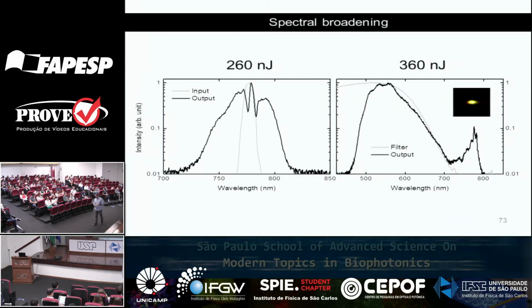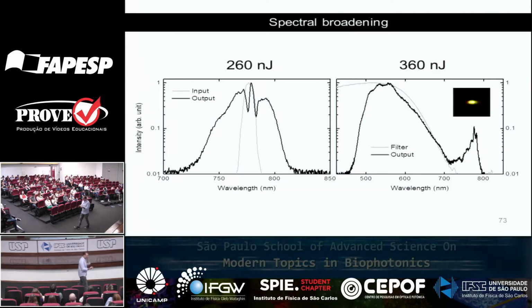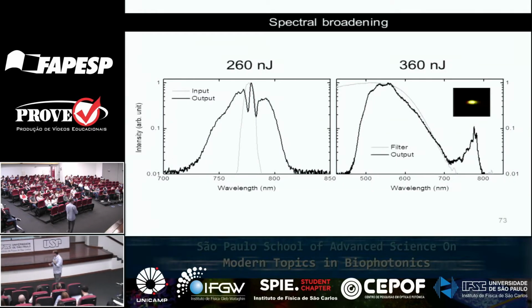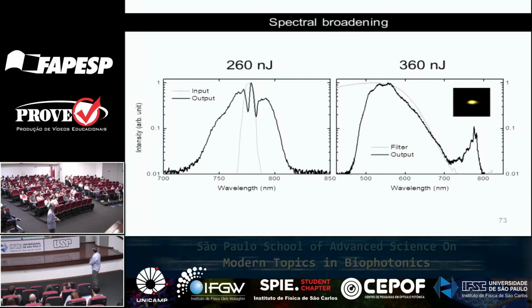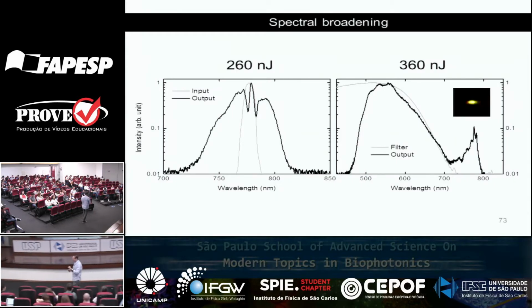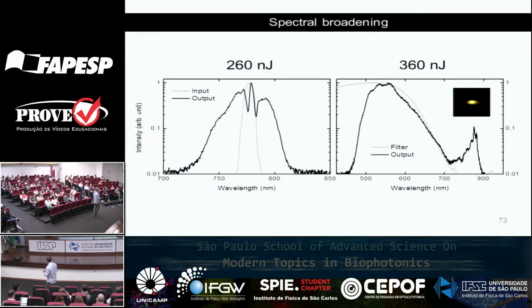Gorilla Glass. So people haven't studied much about the nonlinearities of Gorilla Glass, but we actually did in our lab. So it presents a reasonable n2. So it presents a reasonable chi-3 effect. So when we couple, instead of a HeNe laser, a femtosecond laser in the Gorilla Glass, the nonlinearity is high enough that on the other end, in the output, you can get white light continuum generation. So we can get white light coming out from the Gorilla Glass waveguide. So that's what you see here.